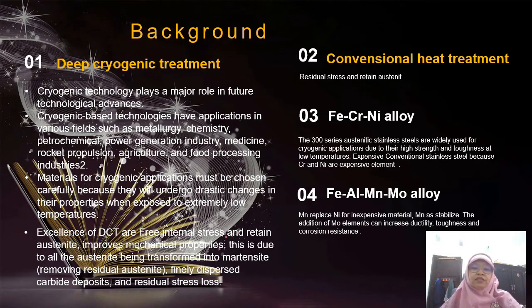However, not all austenitic stainless steel can be used under cryogenic conditions because some austenitic stainless steels undergo structural changes from FCC to BCC at low temperatures so that they lose their ductility and toughness. Another problem with the use of austenitic stainless steel is the high cost of the element nickel and the limited world resource of chromium. At present, various efforts are being made by material engineers to find replacement alloys for expensive chromium alloys and nickel-based alloys. The FeAl-Mn alloy is one of the innovations developed by material research in the world.